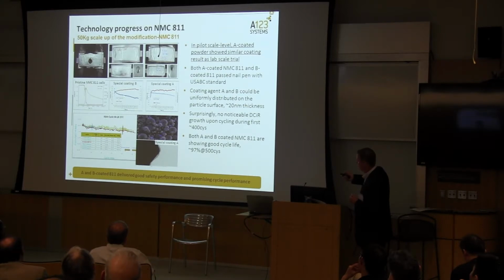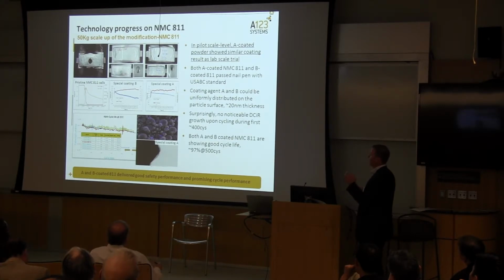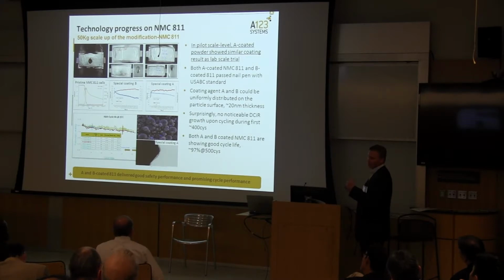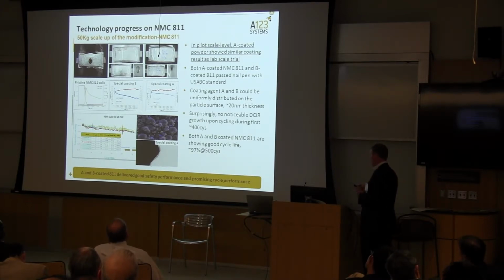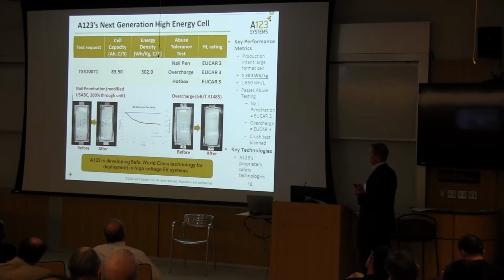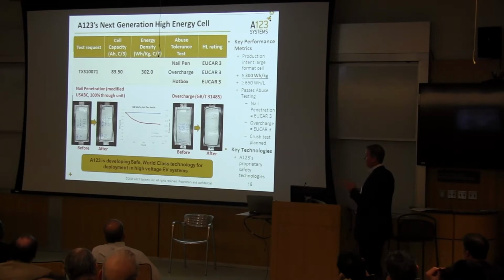So here's the voltage trace versus temperature. What this is doing is it's really mitigating that reaction at the surface that releases heat and oxygen, so that it doesn't react with the electrolyte to essentially start a fire. So that was done with an 811 graphite. Those came in at about 260 to 270 watt-hours per kilogram.